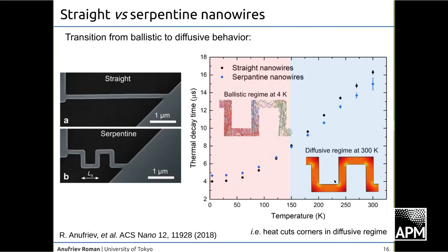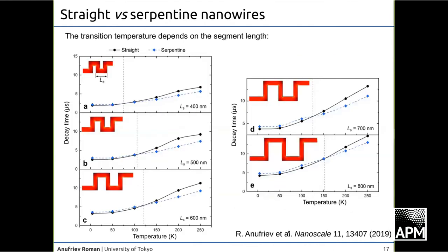Rather here, it can actually cut the corner and go back, go out faster. So it becomes faster in the diffusive regime than at low temperature. And the same thing can be demonstrated as we make structures of different segment length. This way we can probe at which length scale the ballistic conduction is strongest.